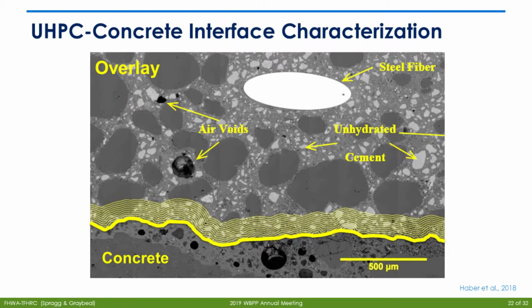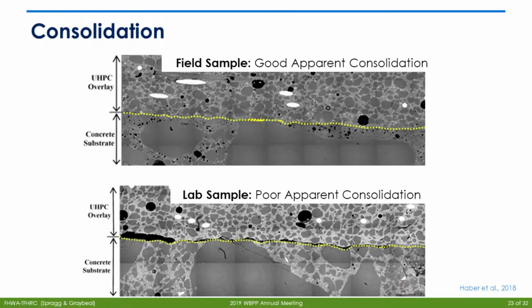Then you can also see the steel fibers. Those are the parts in white. White represents density, so white means higher density. So you can see on average the UHPC is denser than the concrete below it. But when we took these samples from this project in Iowa back to the lab and looked at them under the SEM, we could see that we did end up with cases where there was poor consolidation. So that's one of the key things that we're looking at moving forward: how can we ensure that this UHPC overlay is well consolidated.